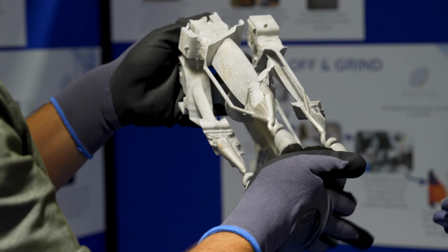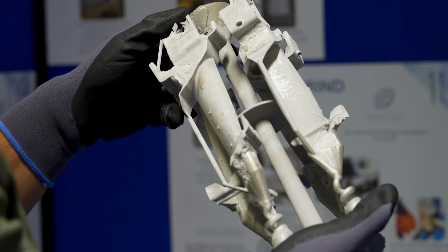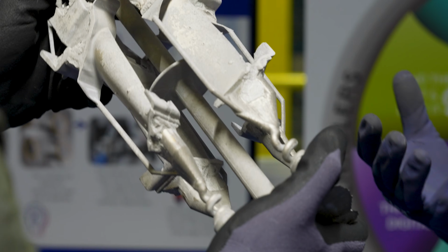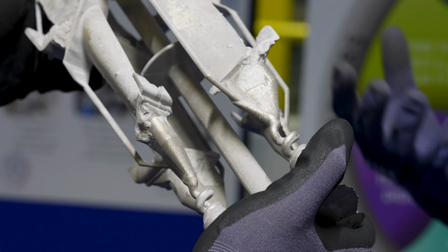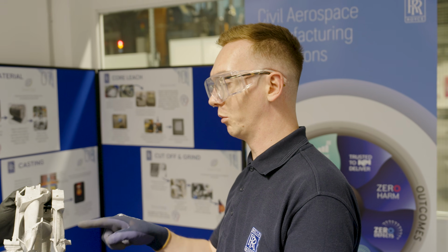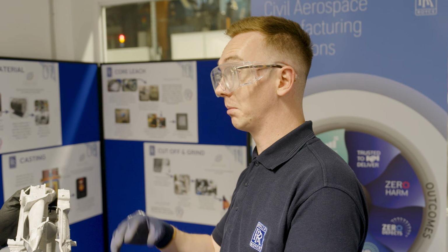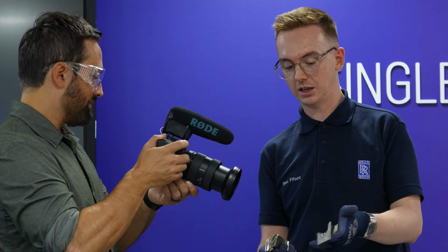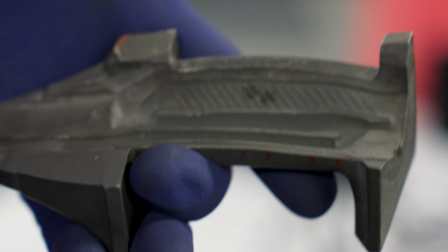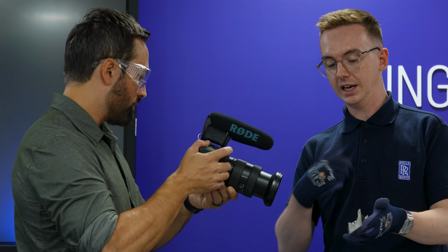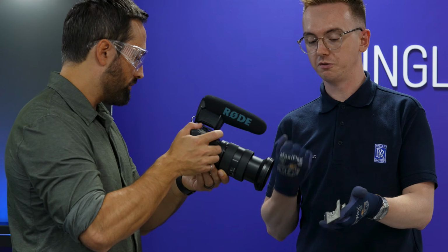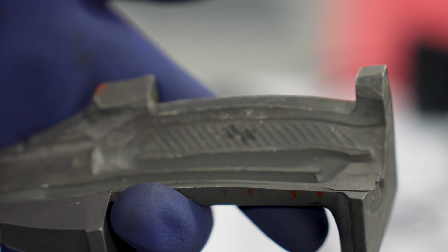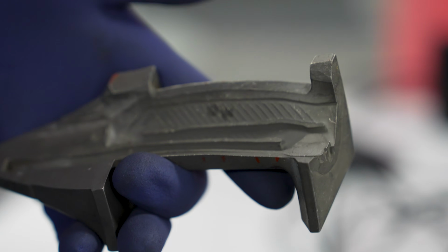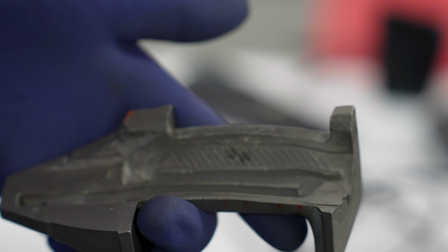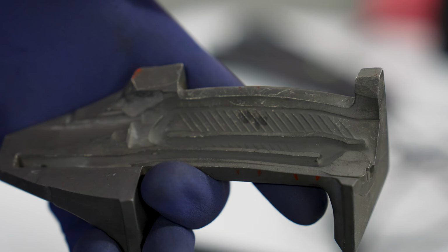We then have to leach the core out, so we do that in a caustic solution of potassium sodium hydroxide, under pressure and temperature. That will leave those core passages completely empty. And those passages are the real secret to the turbine blade's survival. As the air's flowing through, it is turbulent, and as such it can remove much more heat from the surface of the blade than if it wasn't. Is it these ridges here that we're talking about? Yeah, these ridges here. They're intentional to trip the flow into turbulence, to trip and turbulate that airflow so that it's removing as much heat as possible from the metal.